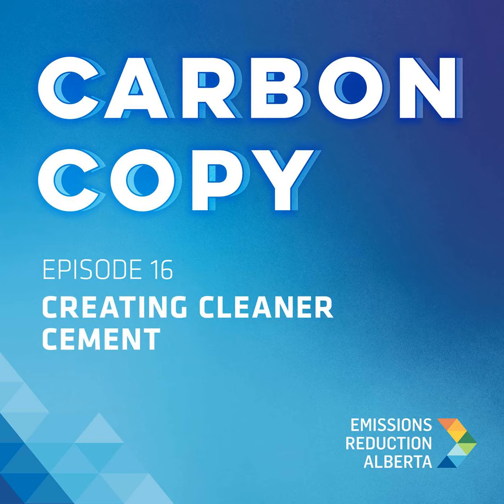Yeah. So we have a limestone quarry at the Exshaw plant. Most cement plants around the world are located right at a limestone deposit because that is the major raw material that's used in the production of cement. So we have a calcium source, which is the limestone. We have a silica source, an alumina source, and an iron source. And typically you have between four to six raw materials that make up these four ingredients that you need. We grind all those raw materials to a fine powder using either a ball mill or a vertical roller mill, and then that powder is stored in a silo.